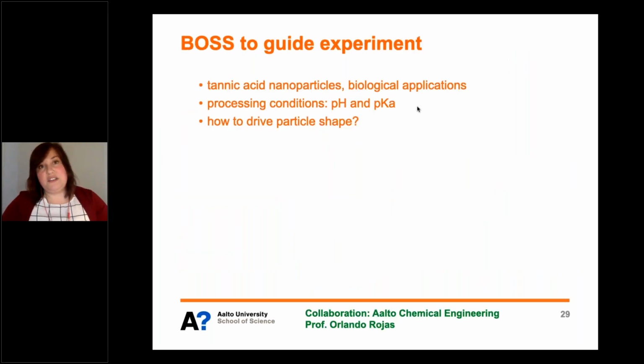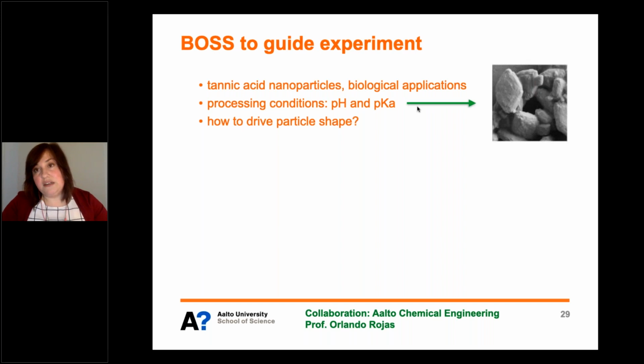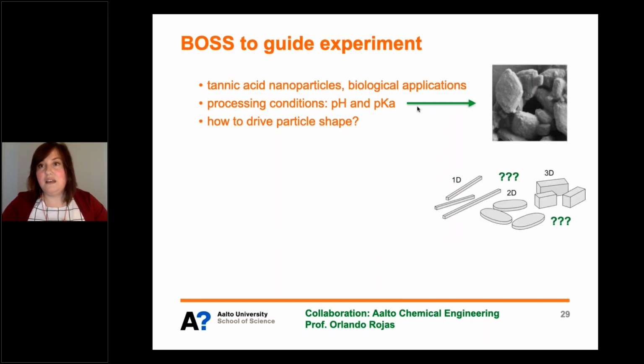The last thing that I wanted to mention is that we've recently tried to use this with experimental data. We were approached by colleagues in chemical engineering at Aalto, and they were building tannic acid nanoparticles for biological applications. And they had these 2 processing conditions, the pH and the pKa of their base solution. And they wanted us to help them drive the particle shape between 1D and 3D. So they made a bunch of particles, looked at them, and tried to extract the dimensions for these particles, and then we constructed an objective function for what makes a 3D shape.